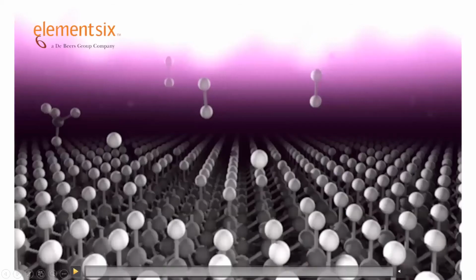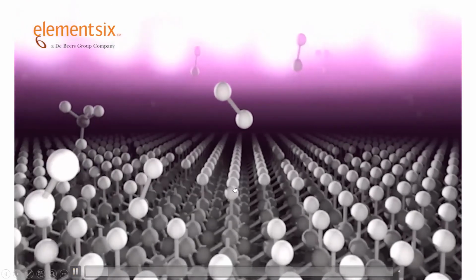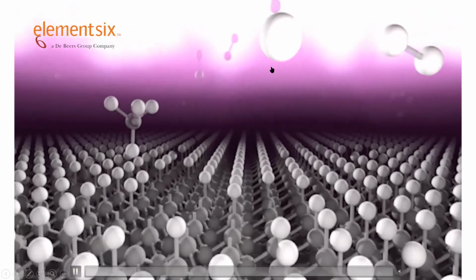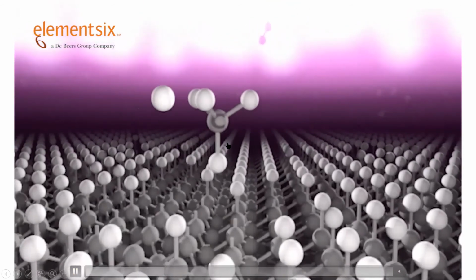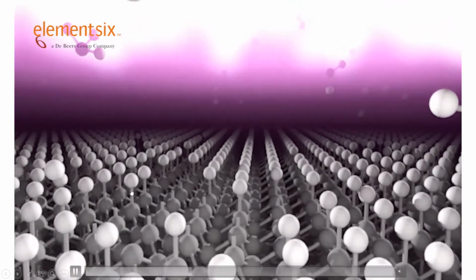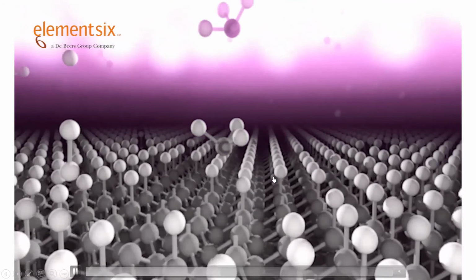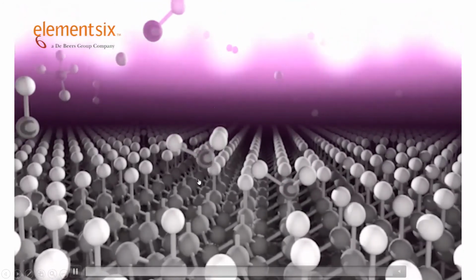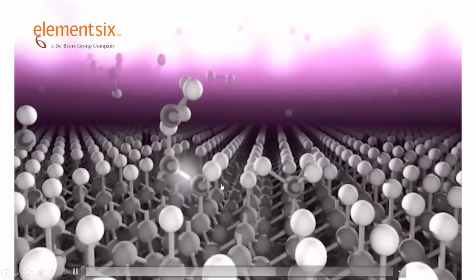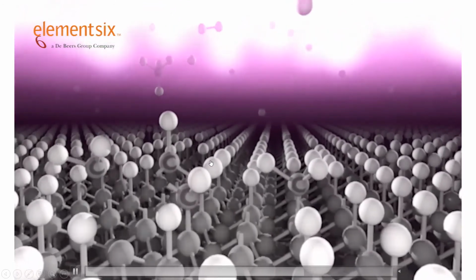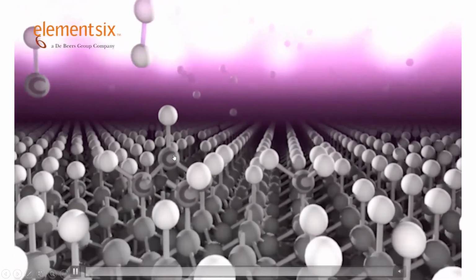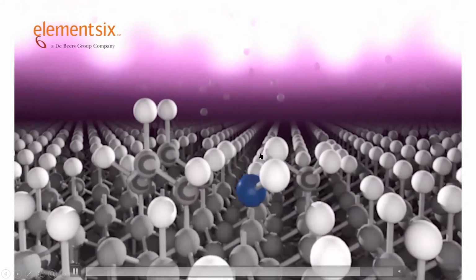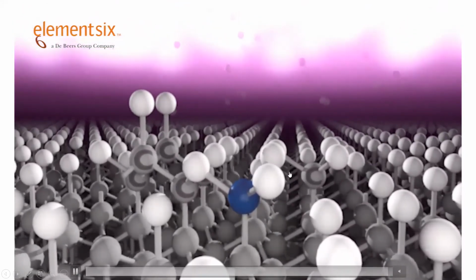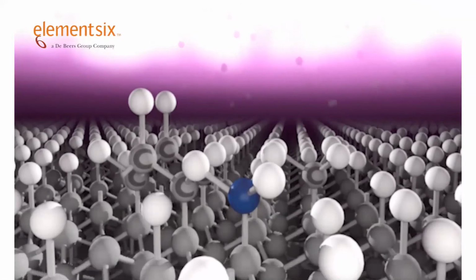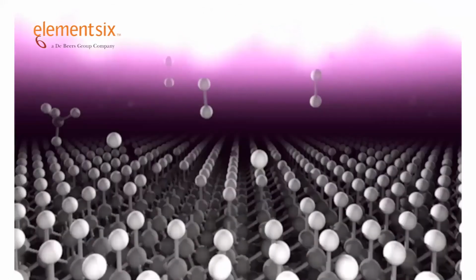And if I go to this video here, this is the diamond surface growing. So what these are, hydrogen gases splitting into hydrogen atoms. This is a methane. So I need one of those CH bonds to break. That hasn't broken there. Okay, here's one that's got a missing hydrogen and it's going to stick on the surface. And this one's going to stick on the surface. And what has to happen is hydrogen atoms need to come along and pick off these hydrogen atoms on the bonds, and then they can have these CH radicals adding. Okay, so this process will happen layer by layer by layer. And this is what's happening now. There's lots of growth labs, lots of companies set up who are growing diamond as we speak for different applications.